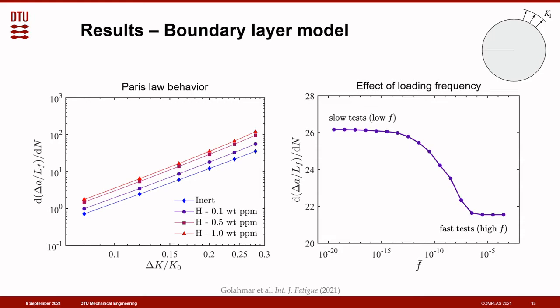On the other hand, we have slow test or low frequency, where hydrogen atoms have sufficient time to accumulate in areas of high hydrostatic stress and therefore magnifying the embrittlement. And you can see how the model easily captures the smooth transition between these two limiting cases.